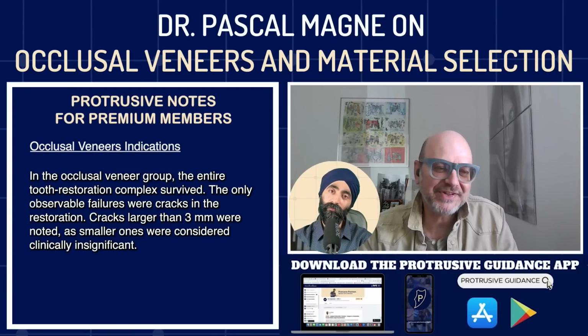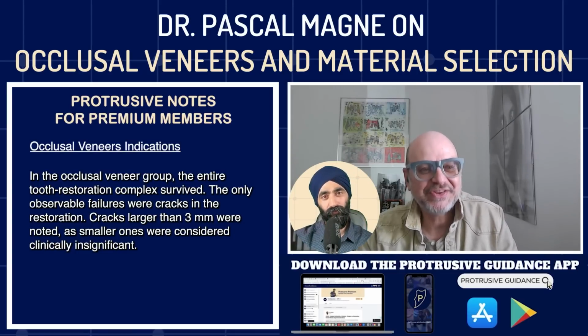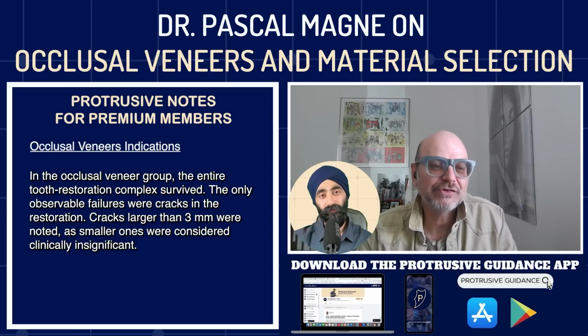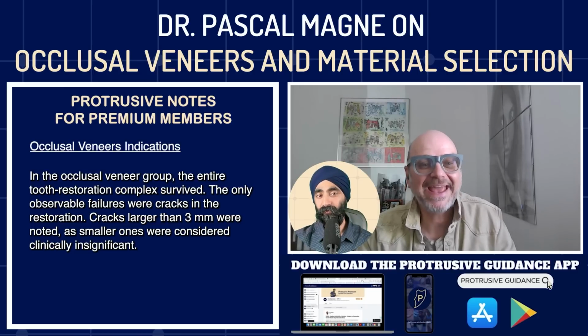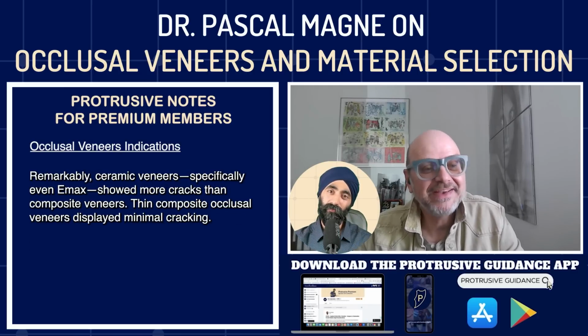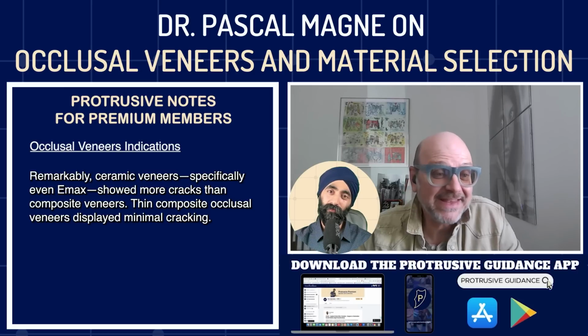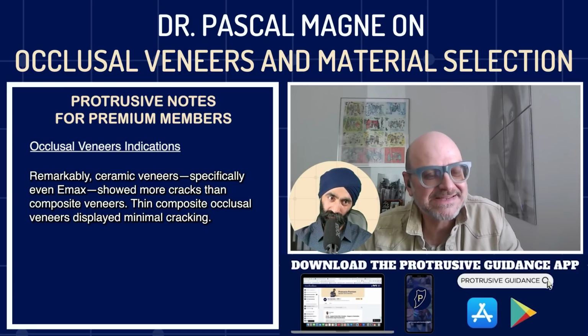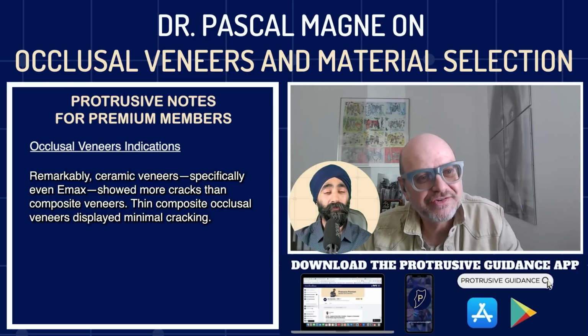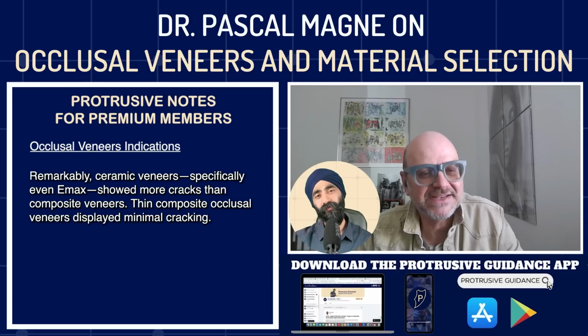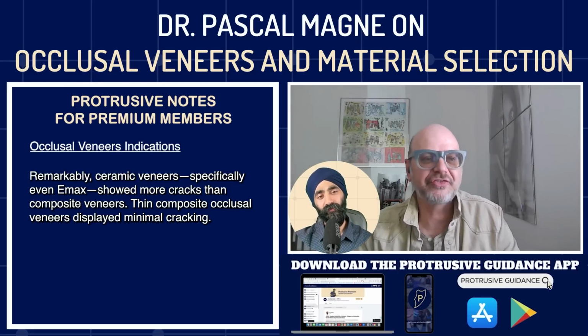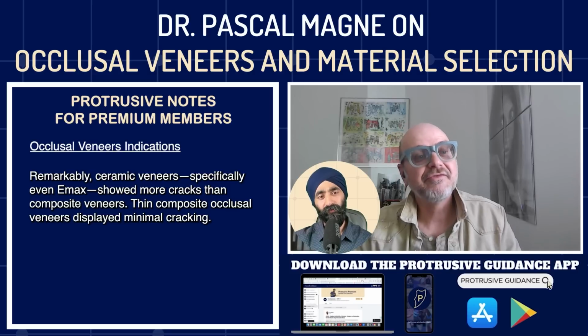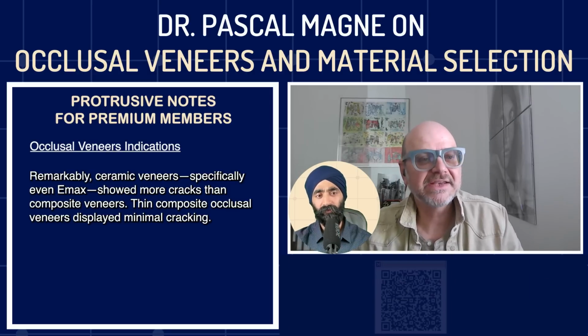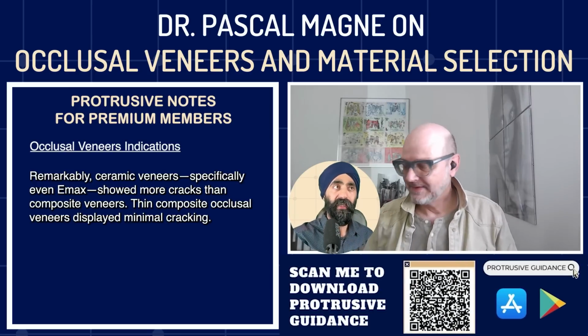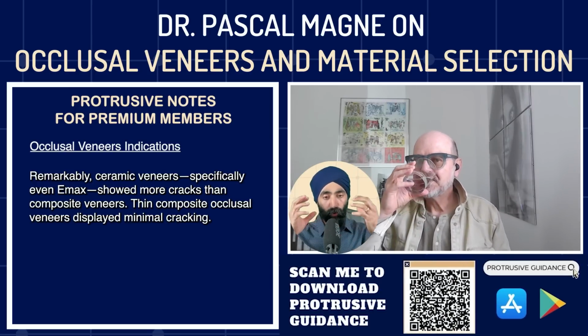So this is amazing. So that's the first message for you. Whether the veneer was 1.2 millimeter down to 0.6 millimeter, the only thing we could see were cracks. And what was surprising in this case is that the ceramic, even Emax, had more cracks than the composite veneers. So this was really surprising. The composite occlusal veneers, thin ones, displayed very little amount of cracking. Now, with the composite, that's very fascinating. But this is a different beast. I just want people to understand that.